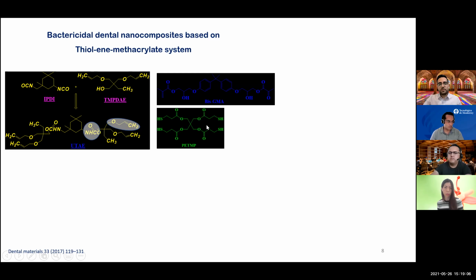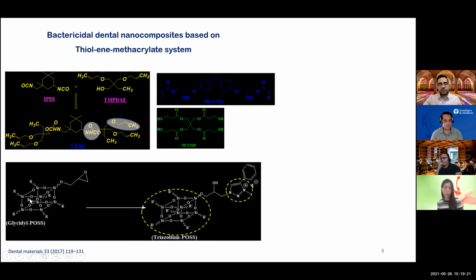At the end, we use the other matrix. It's a thiol because we want to use thiol-ene, and at the same time, we use this monomer with a dimethacrylate system. It's a ternary system: thiol, methacrylate, and allyl ether. And as a filler, we tried to modify the surface of the nanoparticles. It's POSS nano cages with a glycidyl part, and we set triazolium groups on the surface of the nanoparticles. The main reason we did this is that we know that quaternary ammonium, especially in aromatic rings, can show really nice bactericidal activity. They can really show antibacterial activity. For that reason, we are using these nanoparticles that are already functionalized with the antibacterial groups.